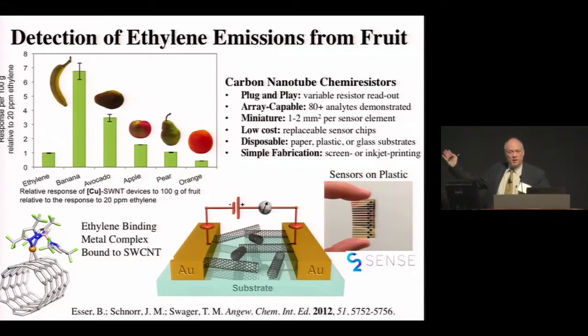One of the ligands comes on and off. That's actually very well known for these type of scorpionate ligands. And it senses ethylene. And now we get a very robust response to ethylene. Nanotubes without this do not respond to ethylene. And we actually went on and did a whole study. You can look at it in this paper, a whole study of fruit ripening over a week's period, different fruits, different temperatures, showed all the profiles. Not all of them have this big hockey stick. Some of them are more gradual in how they go. Some of them go up and go down. But we went through all these different fruits, and we were able to nail their ethylene with this single sensor here.